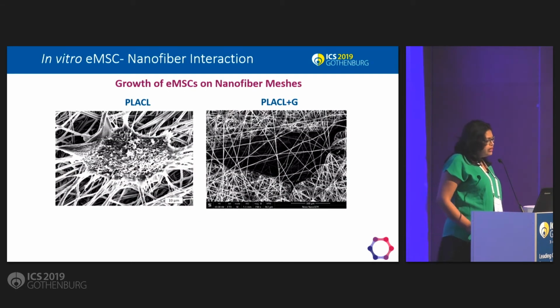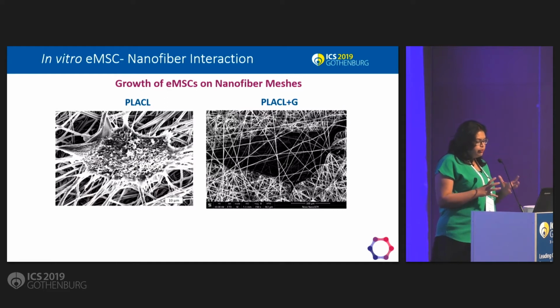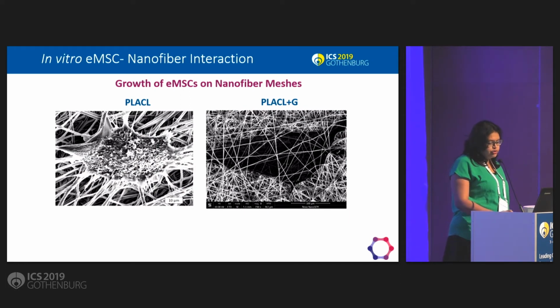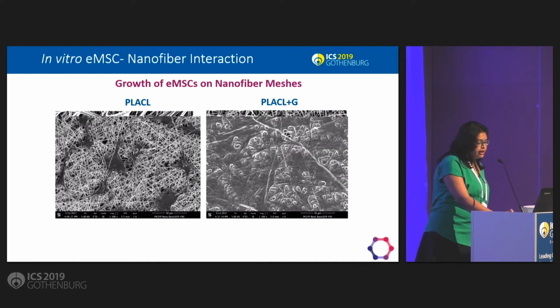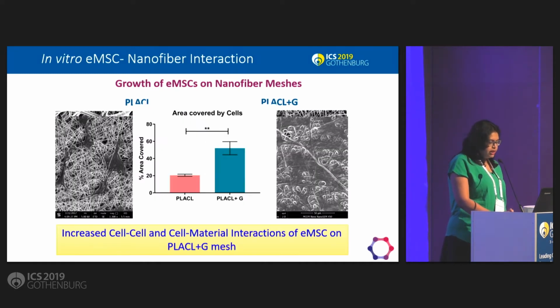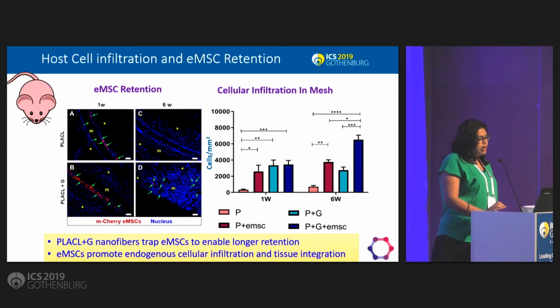Because it was hydrophilic when we added gelatin, what you see is that on mesh 1, the cell is on top of the mesh, whereas when we add gelatin, it enables the cells to go inside and get trapped. So we hope that this will keep the cells longer after we transplant them, so there's more cell-cell and cell-material interaction. When we implanted them in mice, because of this trapping effect, the cells were kept much longer, up to 6 weeks at the site, and there was a lot more infiltration of cells, which was what we desired.